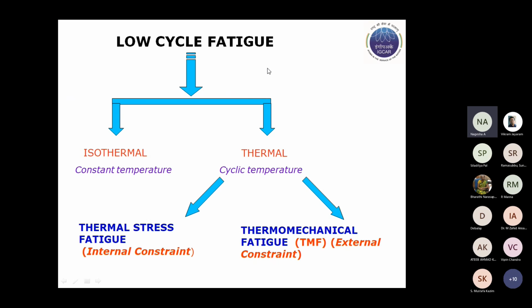Okay, the subject of low cycle fatigue can be broadly classified into two, depending on the temperature of testing. Generally, the conventional testing for generating the design-related data for high temperature structural materials that are exposed to fatigue in service relies on an isothermal database that is generated at a constant temperature. Normally, if a structure goes from a minimum temperature to a maximum temperature, the design data relies on the results obtained from the peak or maximum temperature of cycling.